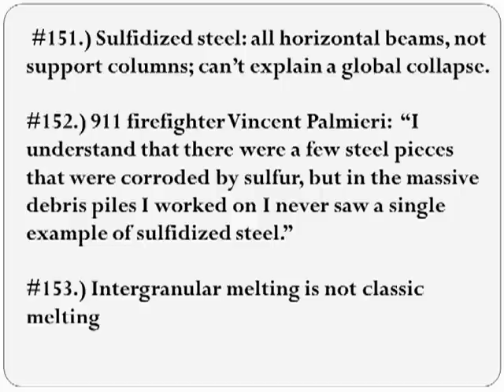The intergranular melting FEMA talks about is nothing like melting as we know it. The steel wasn't molten. The part with the lowest melting point became part of the slag. The long technical term for the sequence of what happened was intergranular melting, high temperature corrosion via sulfidation, oxidation, and decarburization leading to a liquid iron oxide sulfur mix from grain boundary melting in a very, very small quantity, around 20 microns wide. No, I don't really fully understand that either, I admit.